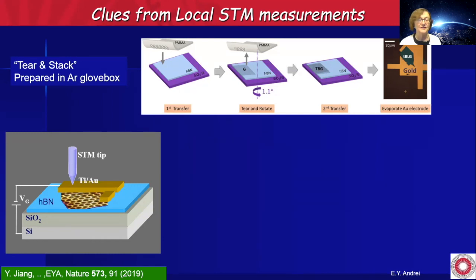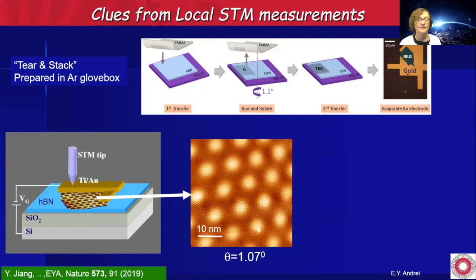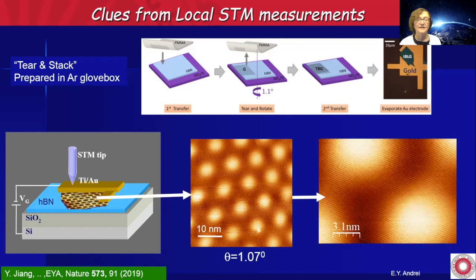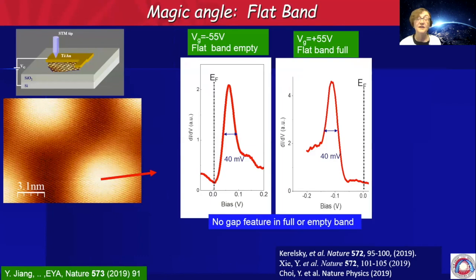So here is the topography. This is a sample that is twisted at a magic angle. This is the Moiré pattern, which has a period of 13 nanometers. And this is a zoom in, so you see the individual atoms in the AA regions and AB regions. And next we looked, now that we could gate the system, we put our Fermi energy so that this flat band, we see that this is a flat band now, it's fairly narrow, 40 millivolts. So we could go and search on this sample.